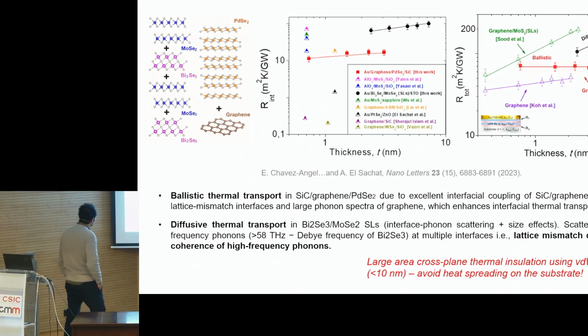Yes, because we are in the case not of the superlattices, but of the palladium diselenide. So imagine here we have silicon carbide, and we grow this by CVD. We have excellent thermal coupling. The graphene, in the best case scenario, has to be grown on silicon carbide. This is the perfect way to grow graphene. With this way, you have very, very small thermal resistance between the graphene and the silicon carbide. Actually, almost zero. And then we grow the palladium diselenide. The palladium diselenide with graphene has zero thermal mismatch.